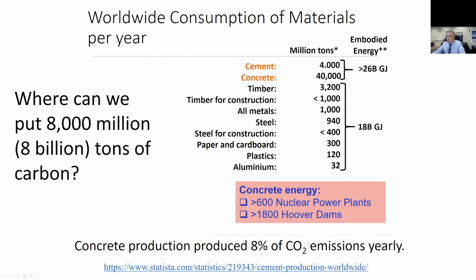So if you can cut down the amount of concrete, to give you the numbers, we put less than 1% of graphene into concrete, and we increase the compression modulus by 30%, and we increase the tensile strength by 20%. So think about using 25 to 30% less concrete, the amount of CO2 emissions that you save. So you save in CO2 from the use of the graphene, you save in CO2 from the change in the CO2 emissions. So this can overall have a huge effect.